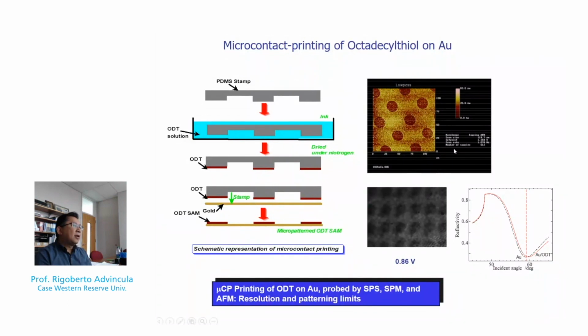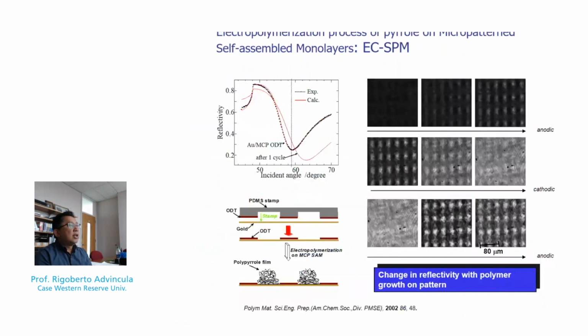Here is actually the AFM micrograph of the patterned deposited film based on self-assembled monolayer pattern surfaces, where the polypyrrole selectively deposited on the dots. And here are optical micrographs showing the changes in intensity with deposition, as well as the changes in intensity as you go in and out of the Plasmon curve of the deposited film. So for clarification, this experiment actually is an SPR imaging setup. So the images you see here are actually optical images as one goes in and out of the dip on the curve, indicating the changes in the dielectric media as a function of, or investigated with, a specific shift in angle.